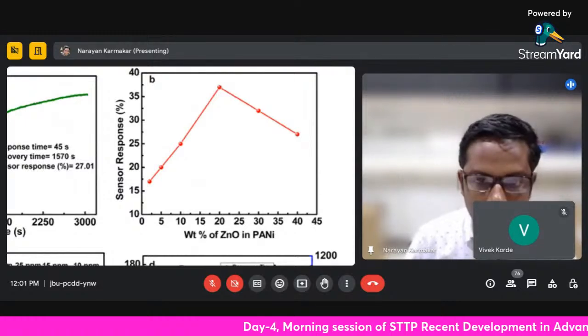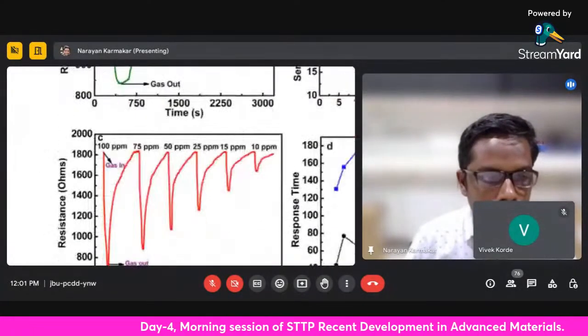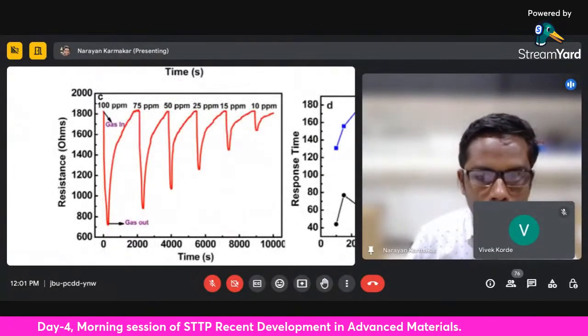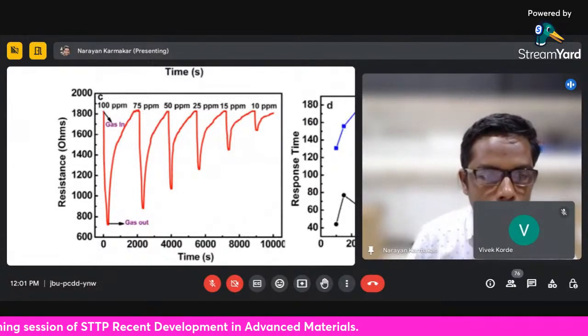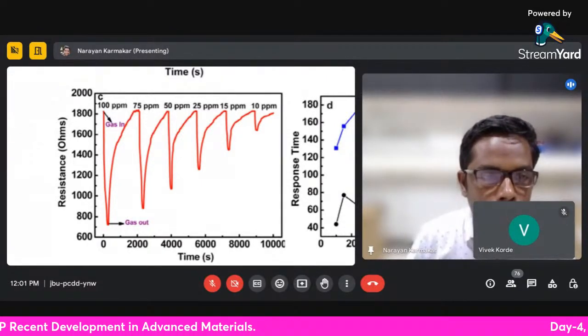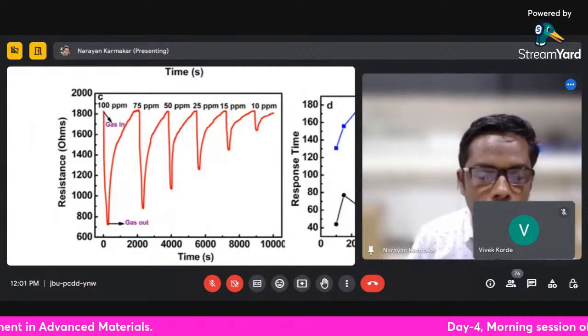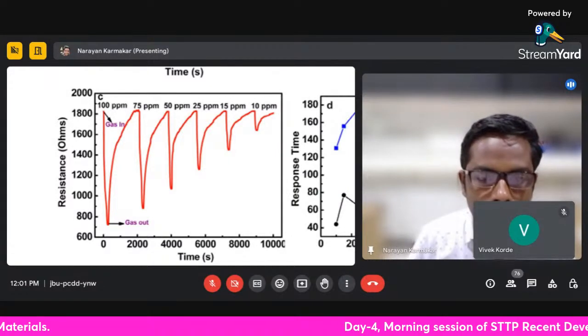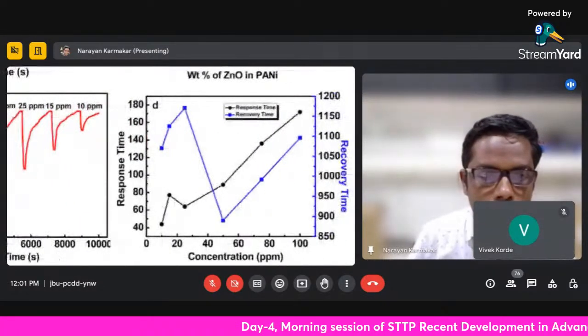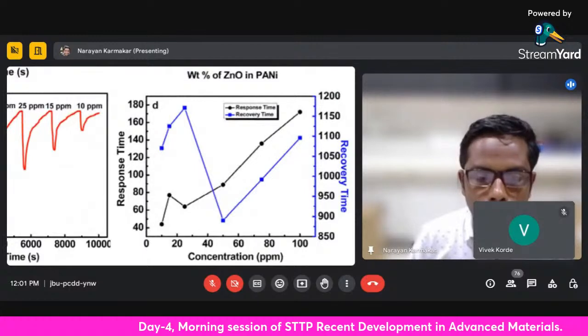Then we studied the variation of this doped ZnO-PANI composite in the presence of different ppm of gases, where it was able to clearly sense down to 10 ppm of gases. But the problem was that the response time and recovery time were not so improved.